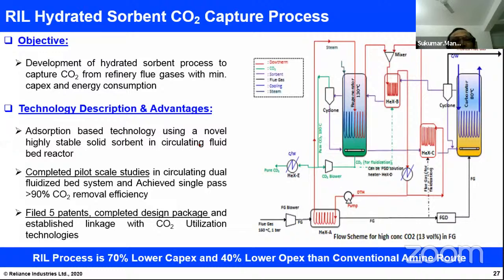So briefly I will explain that the RIL hydrated sorbent CO2 capture process is a two-bed process. You get the flue gas, and that flue gas is compressed, and then you do the heat exchange. Whatever low heat is there, you take this heat out. That goes to the FGD where the CO2 and SO2 are captured. And then this is the vessel, a carbonation vessel. There CO2 capture is taking place at a temperature of 50 to 80 degrees centigrade.